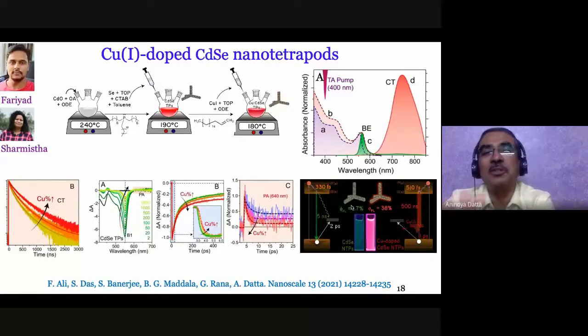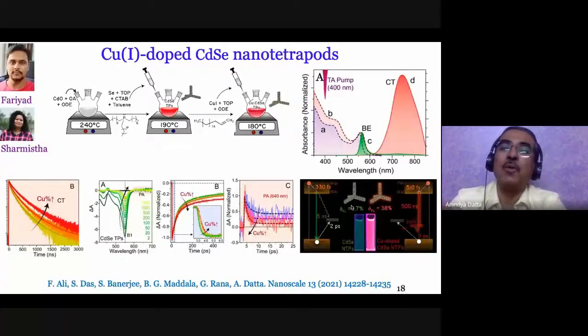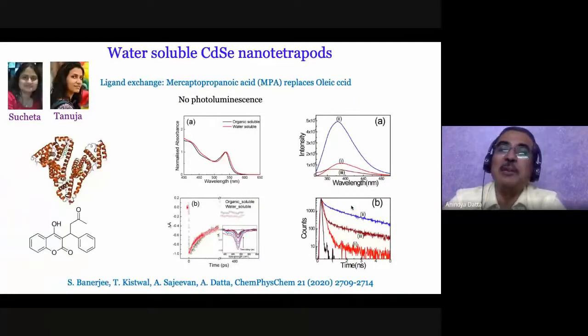And to cut a long story short, using our time resolved spectroscopic methods, we could figure out what exactly happens after excitation and why is it that the copper doped nanotetrapods are so much more photoluminescent compared to undoped ones. We worked out the time constants associated with trapping. We worked out the time constants associated with tetrapods. So we were successful in building a complete picture of the photoprocesses that take place. And this gives us an idea of what kind of strategy one can use to enhance the photoluminescence of nanocrystals like this.